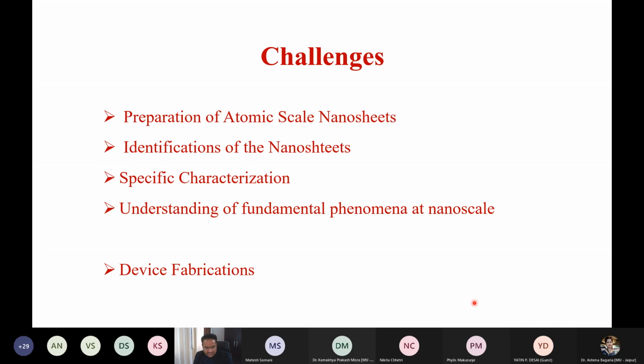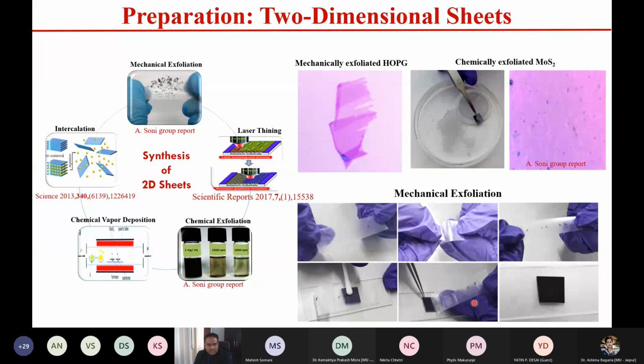Of course, device fabrication is an aspect where a lot of people have been working. In our group, we use solution synthesis as well as mechanical exfoliation of these layered materials using the Scotch-tape method. So a lot of people are using mechanical exfoliation. There are people who use laser thinning of the material, where you put a high power laser on the material and burn the top layers, so what you have is only the monolayer sticking on the substrate. Or you do intercalation and then exfoliate it by solution methods. In our group also, we do a lot of solution chemistry. There are people who do chemical vapor deposition to grow these films on the substrate.